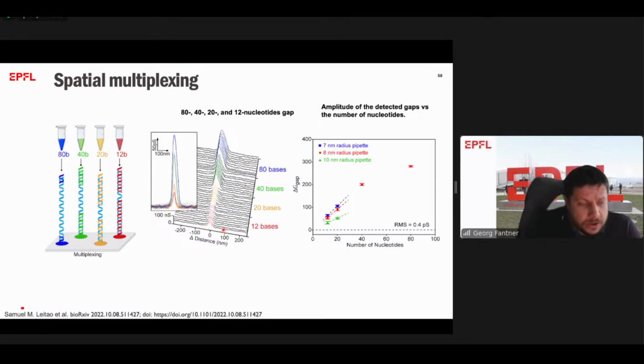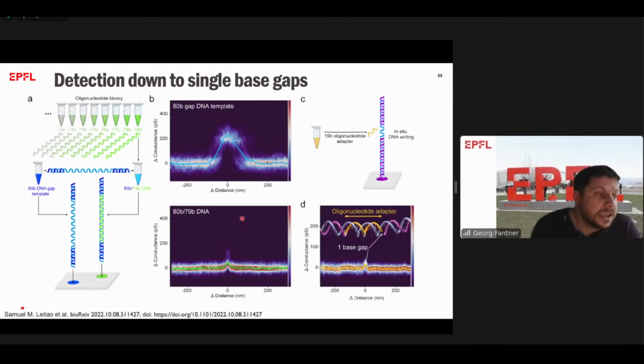And so we thought, well, how far down can we go? Can we go down to actual single base gap resolution? In order to do that, we made a trick. We used a bigger gap. We used one of the 80 base gaps, and hybridized to it the complementary strand that had 79 bases. So that left a single base gap.